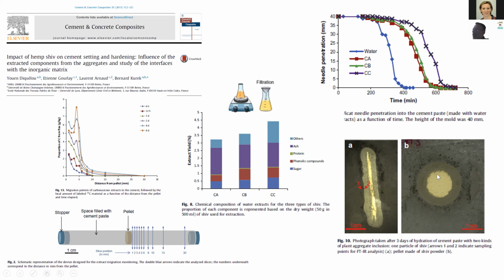This zone, this area, is an area where there is no hardening of the material, and you see it's very clearly defined. When you look directly at the shiv here, you see there are two different places. This is hard, so the concrete is good, in fact. And here is a place where the cement has not hardened.